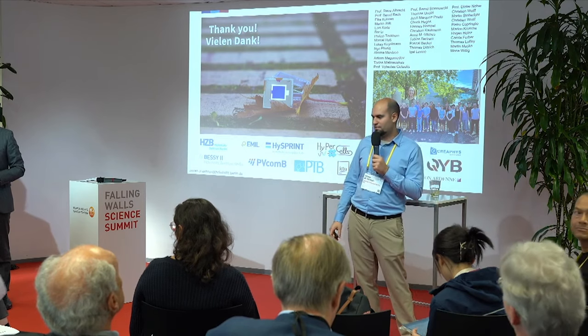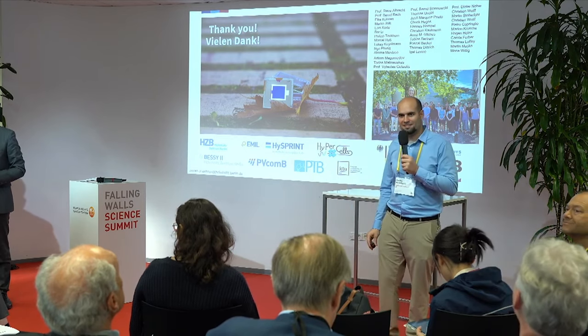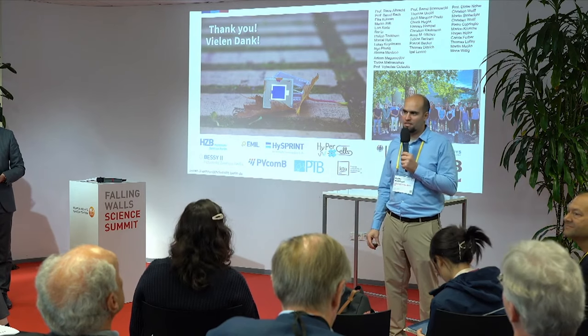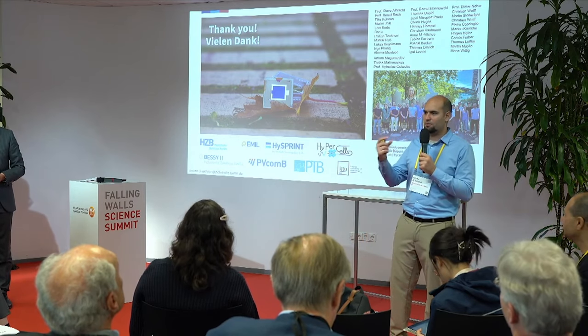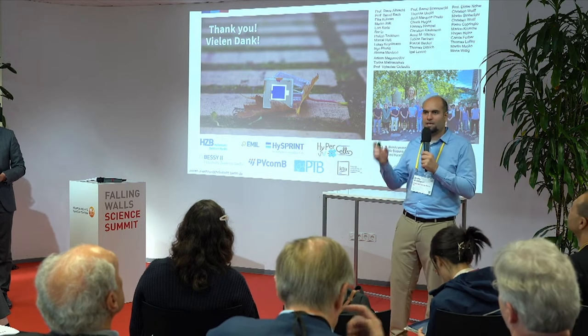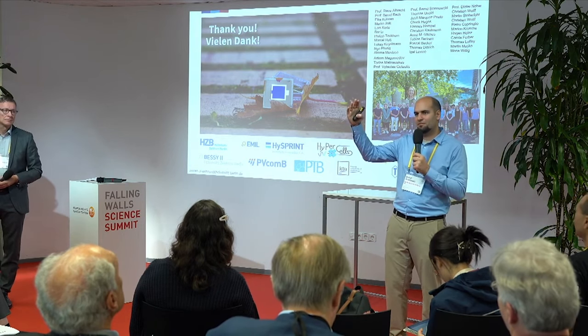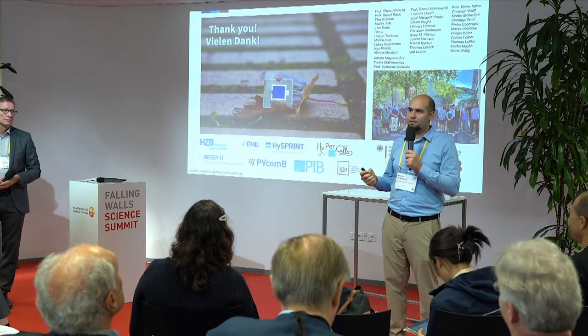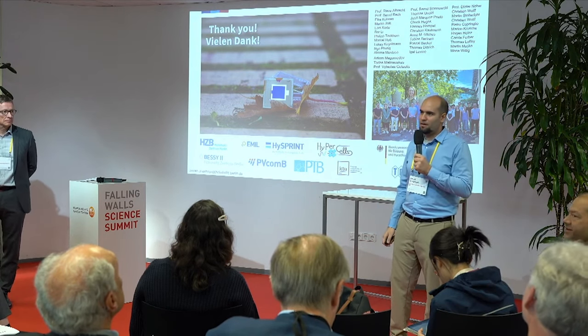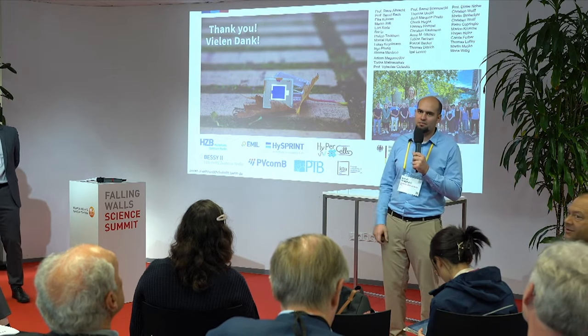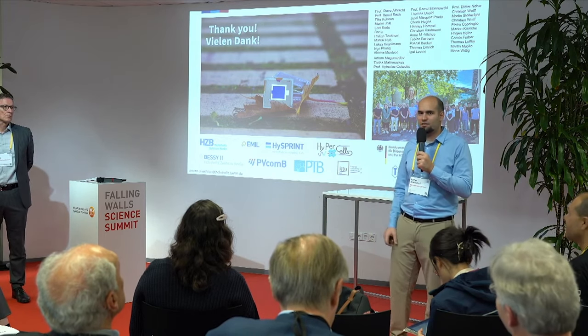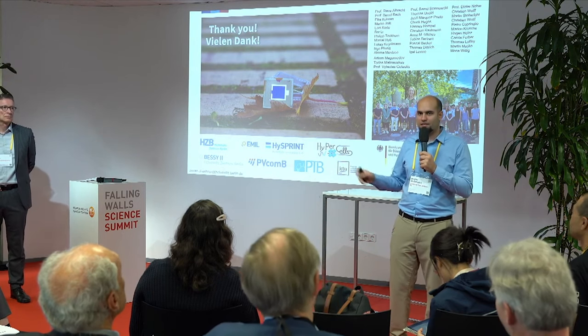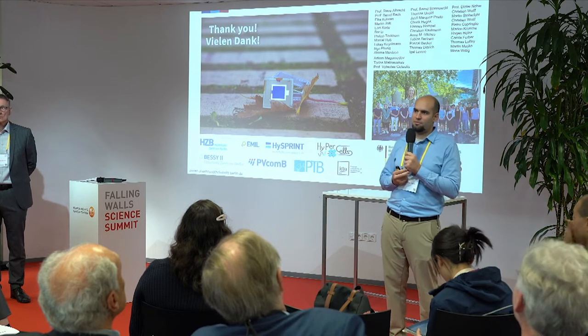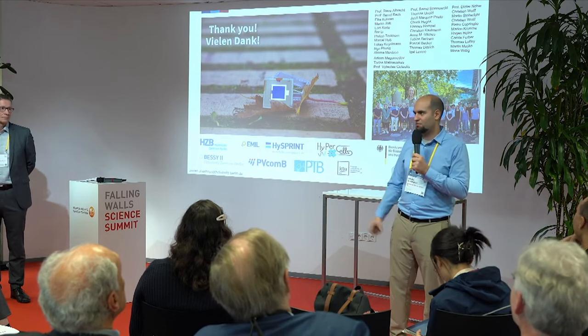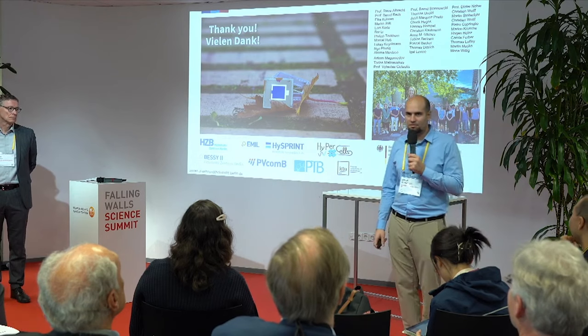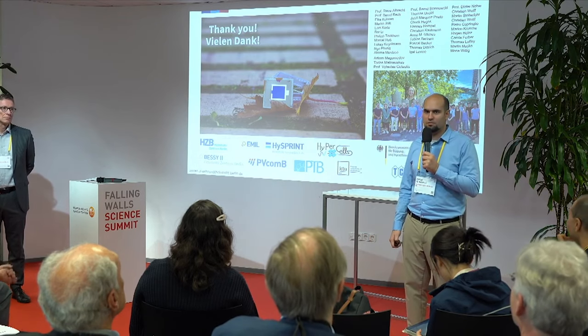Yeah, that's a question most perovskite researchers fear, because actually stability is maybe the biggest issue, because it's an organic, a malleable, soft material, basically. The ions move, and sometimes you're lucky and the ions move to the right interfaces to increase your efficiency. But now there are accelerated aging tests, for example, 2,000 hours at 90 degrees, and they remain stable if you do everything correctly. But I would say it's still far from silicon. You can test outside for 1 or 2 years, this is fine, but not the 30 years of silicon. There's still research to be done.